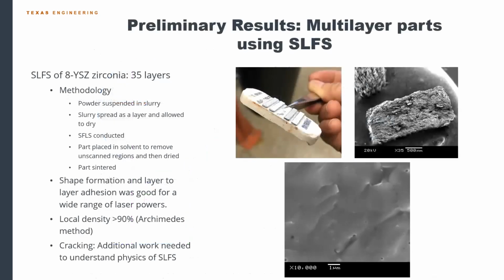This slide highlights the capabilities of this process. We are able to produce multi-layer parts; this one is a 35-layer part. We can also make pretty dense parts, I think on the order of 90% local density, but there are still some challenges to work out. The bottom SEM images show that there's still some cracking, which we're working on now.